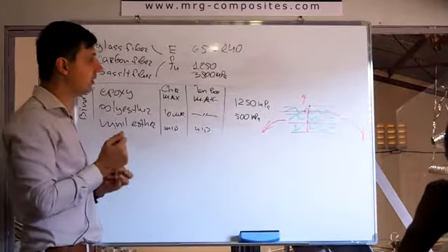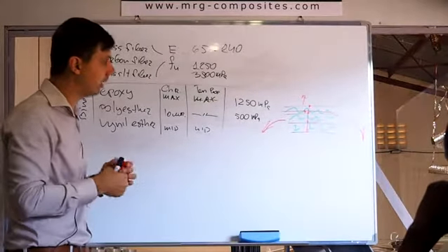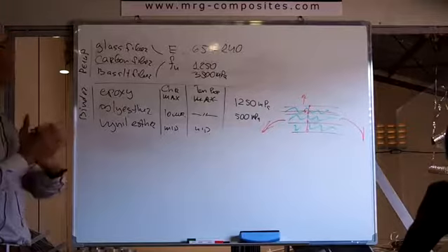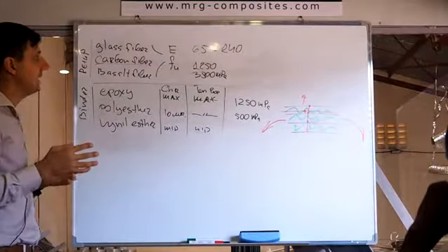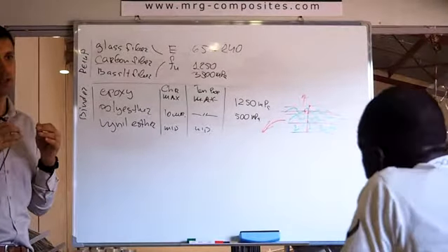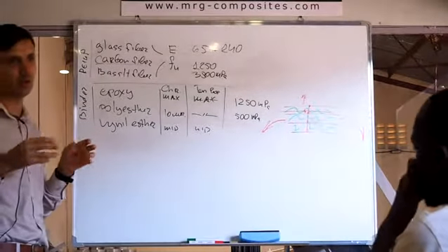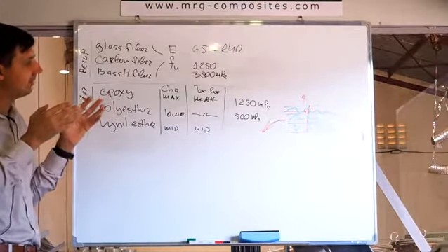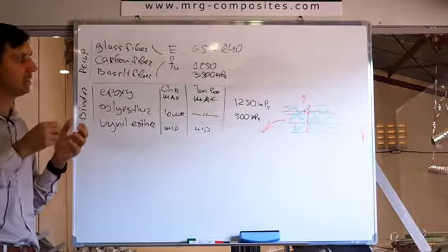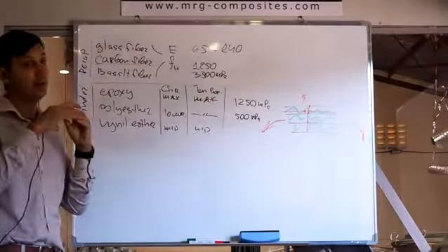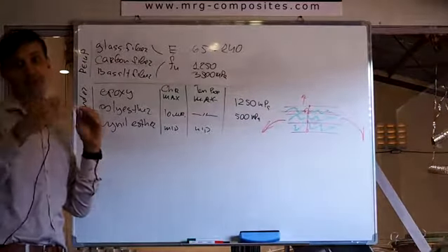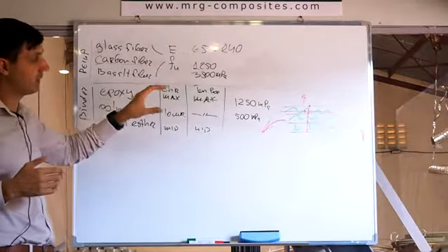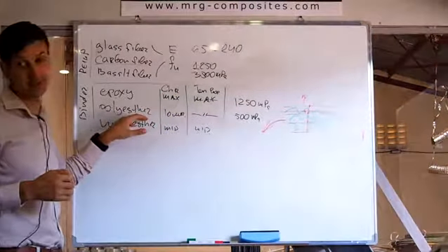Another thing I want to mention is chemical resistance. First of all, with glass fibers, once glass becomes a thread, the chemical resistance of glass itself is not so big. Once it's like this, it's pretty cool, because you know all the chemistry dishes are made of glass. But for this material, glass has no such huge chemical resistance. So another purpose of the binder is to cover the glass to protect it from the action of chemicals. In terms of epoxy, it protects much better than polyester resin.